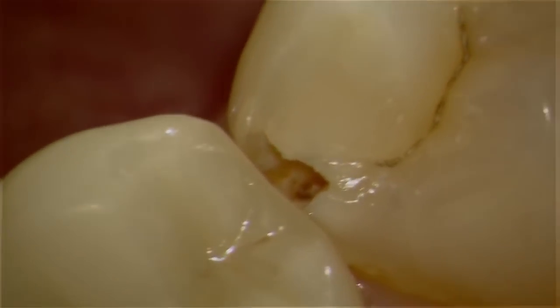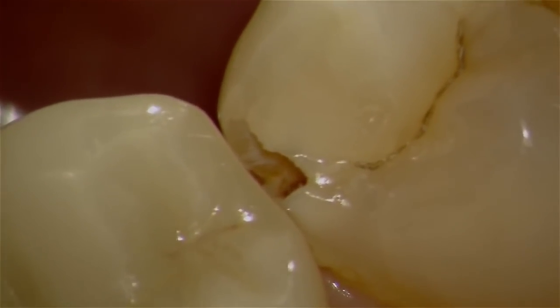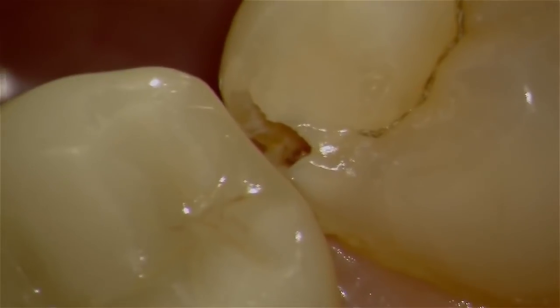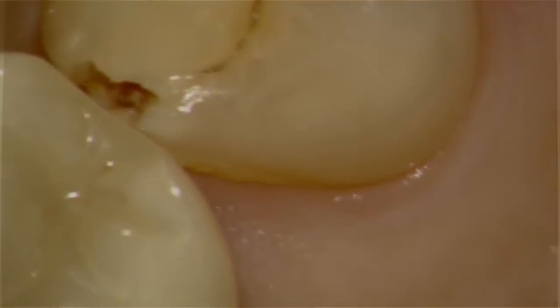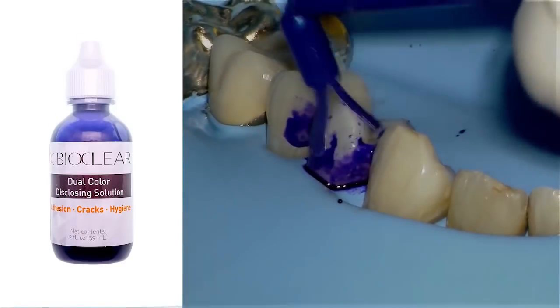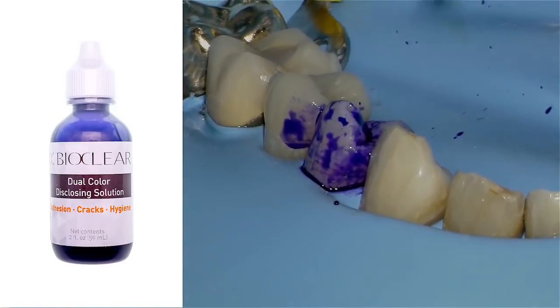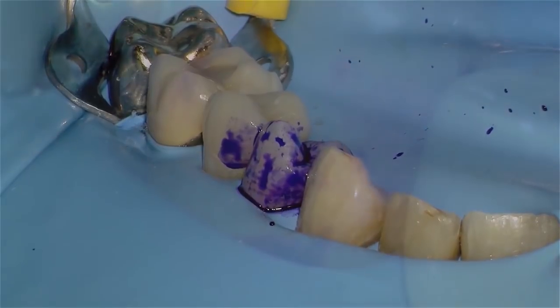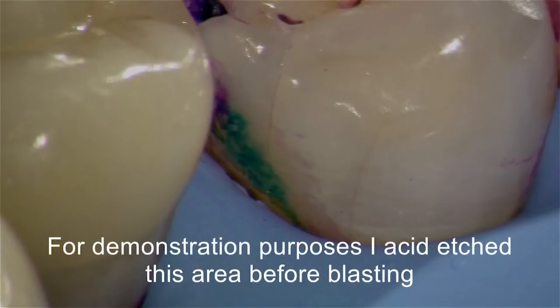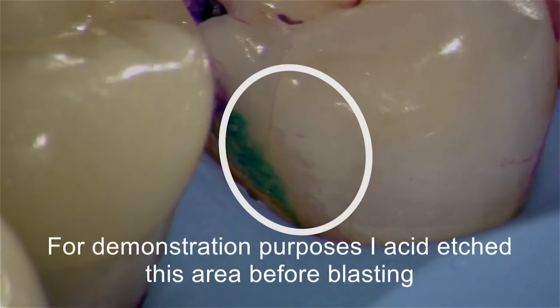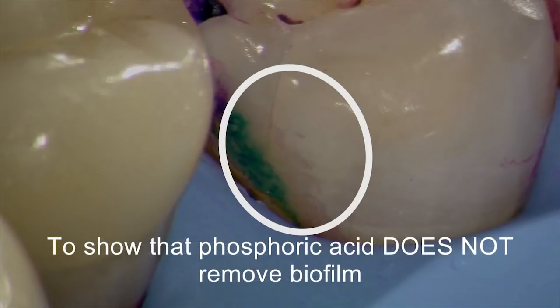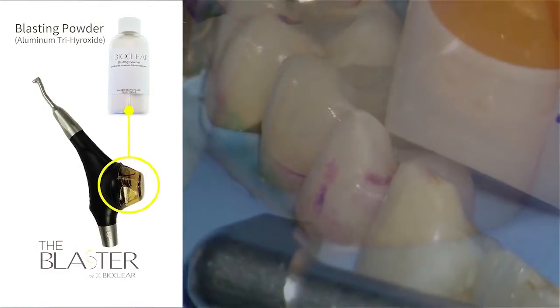We've got this pumpkin shell caries going on. We know that cavity progression has changed in the era since GV Black. We've got fluoride that has changed it, and so the outside of the tooth is intact and the inside is very badly decayed. There's the two-tone disclosing solution, and so it's critical that we do that. And this is really interesting. I actually went in and put acid etch on that spot right there and waited for 20 seconds. You can see that phosphoric acid does not remove biofilm. Let me repeat, phosphoric acid does not remove biofilm.